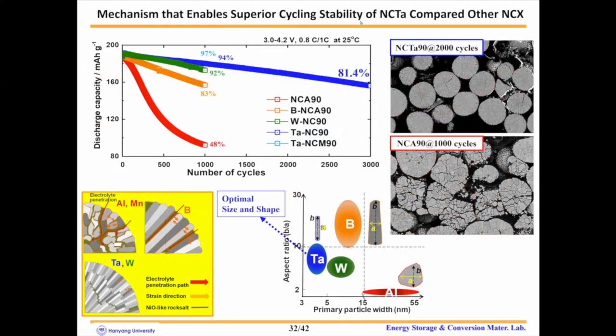This is the mechanism that enables superior cycling stability of NCTa cathode materials. As you can see, compared to other NCX cathodes, the tantalum-doped cathode exhibits the best long-term cycling performance, and the cross-sectional SEM image confirms the morphological integrity of the NCTa cathode materials. We found that the microstructure of the primary particles depended on the dopant, and concluded that there is an optimum microstructure, such as aspect ratio and primary particle width, for achieving long-term cycling performance.